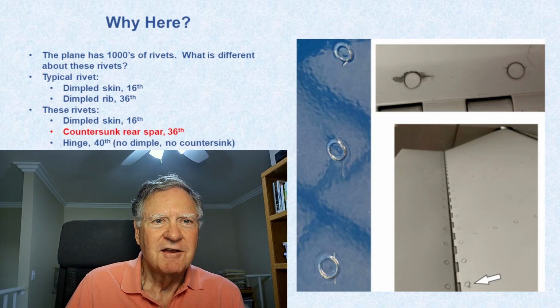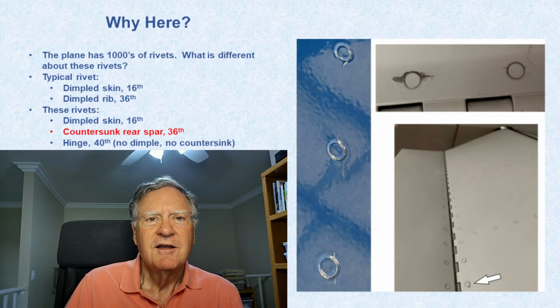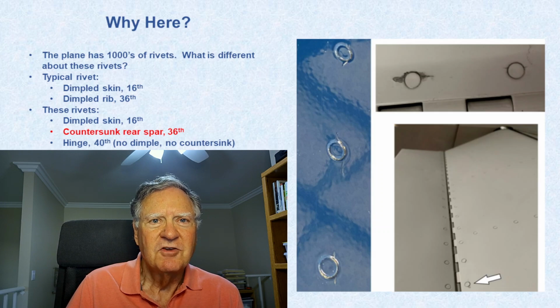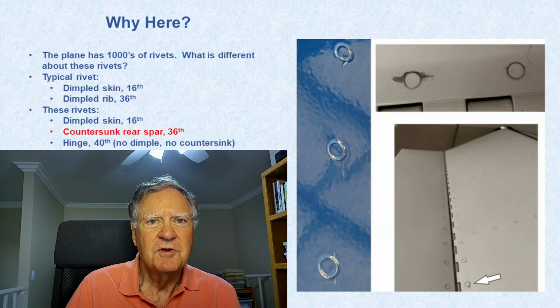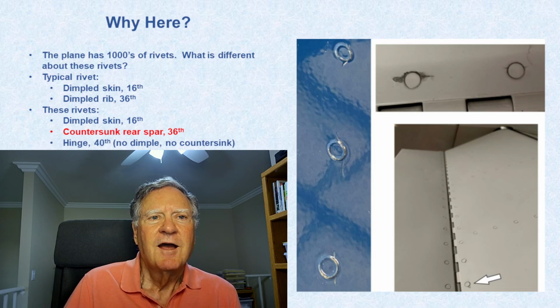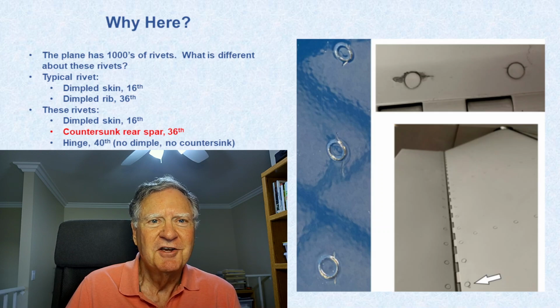Well, these rivets, instead of having just 2 layers of metal, they have 3. The top layer is skin, just like before, and it's about 16 thousandths thick. Then there's a middle layer, which is the rear spar, and it's countersunk, and it's about 36 thousandths thick. And then the bottom layer is the hinge, and it's about 40 thousandths thick, and it's just flat. It has no dimple and no countersink. So one thing that should jump right out at you, in particular, since it's in red on this slide, is the fact that the rear spar is too thin to countersink, or at least marginally too thin to countersink.